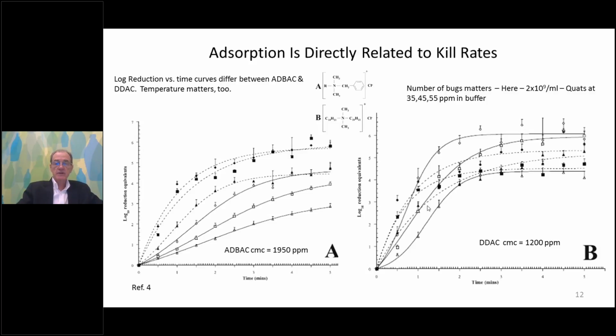And the difference in the adsorption is directly related to the difference in the kill rates. So again, we have on the left our ADBAC and on our right our DDAC quats compared. And we have again on the y-axis log reduction, that's the number of bugs killed, versus time. We've got 3 different concentrations of each of the quats, and they were run at 2 different temperatures in this reference. But it's really clear that on the right, the DDAC adsorbs more rapidly, adsorbs to a greater extent, and it kills more rapidly compared to the ADBAC on the left. So the adsorption isotherms are directly related to the kill kinetics.